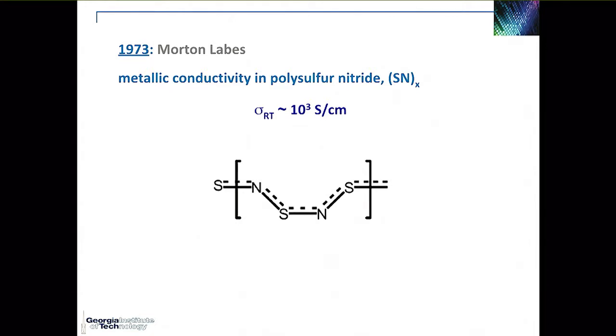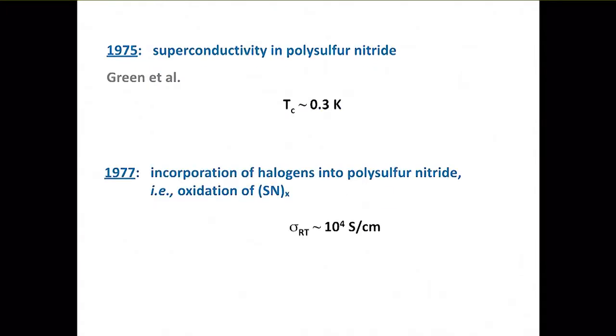So SNX is actually a pi-conjugated polymer, of course not an organic system, along the chains of which you have sulfur and nitrogens alternating with bonds between sulfurs and nitrogens of the same length. And that's what leads to the fact that it is a metal. It's interesting also, that's a bit on the side, but SNX is still the only polymer that has been reported to become a superconductor, albeit the transition temperature is pretty cold.